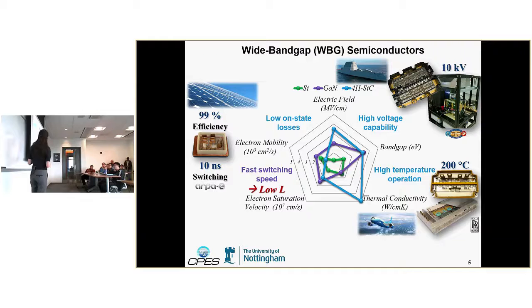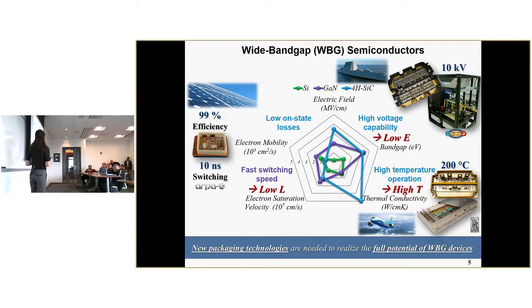But in order to achieve these numbers, you can't just have the semiconductors themselves. You need a way to package them and to incorporate them into your system. So for fast switching speed, you need to have low parasitic inductance. For high temperature operation, you need components capable of operating reliably under high temperature conditions. And for high voltage, when you want to get high density, you need to worry about electric fields. If you have electric fields that are too high in certain areas, you could get very high energy discharges that will degrade the dielectric materials in your system. So new packaging technologies are needed in order to realize the full potential of these wide bandgap devices.